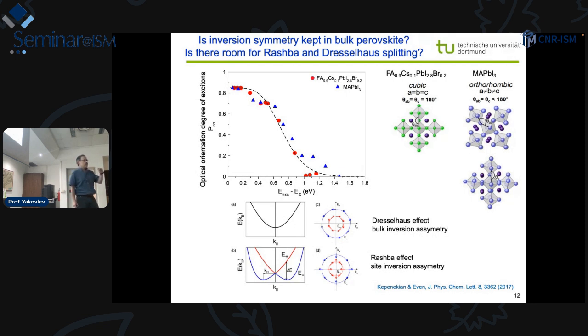there is a small if. The if is that it's not sufficient only to reduce the symmetry, for example, from cubic to orthorhombic. This doesn't remove the inversion symmetry. You need also to find some mechanism which shifts the atom in the middle to one of the sides and which reduces the inversion symmetry. But whether this if happens or not for the bulk materials, or maybe on the surface it may happen, for the bulk material it was not clear.